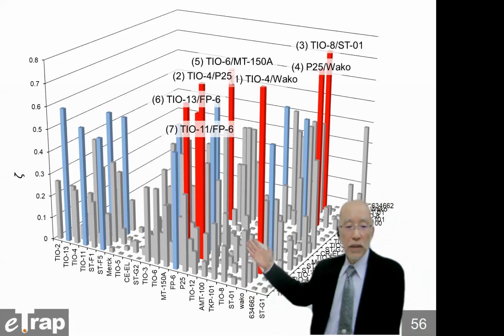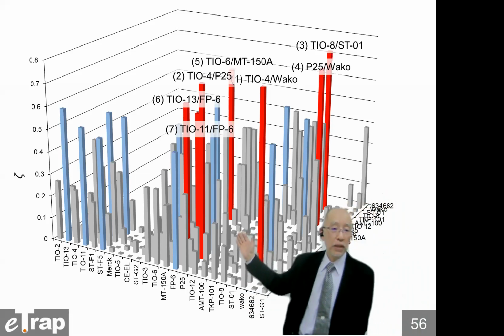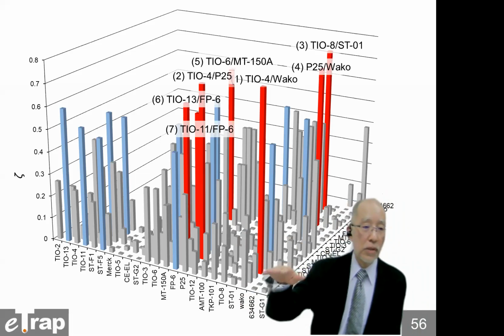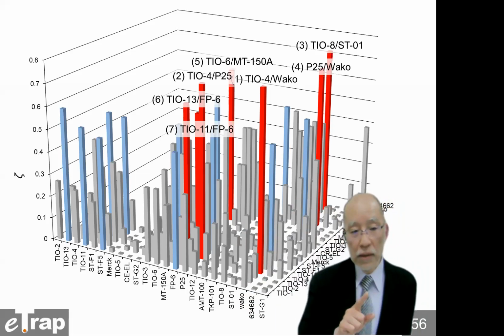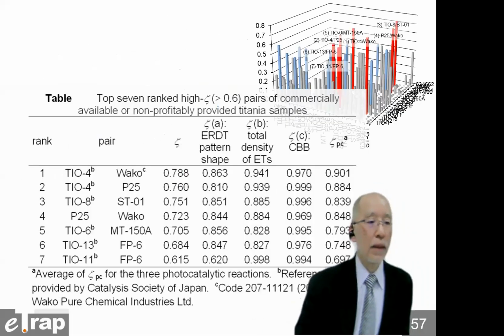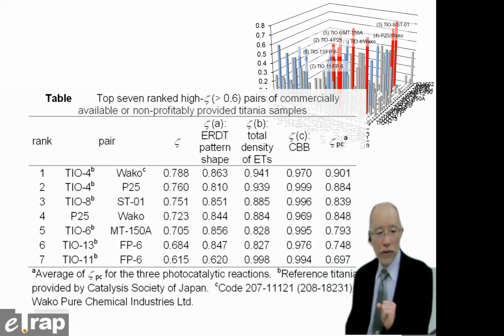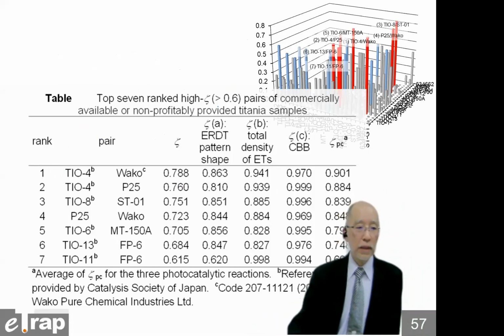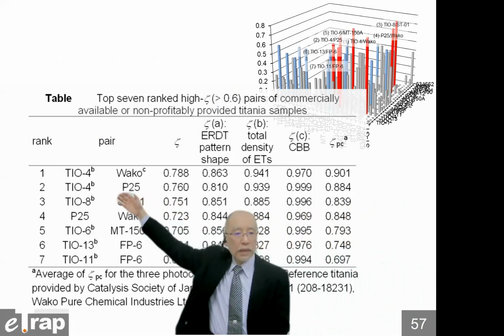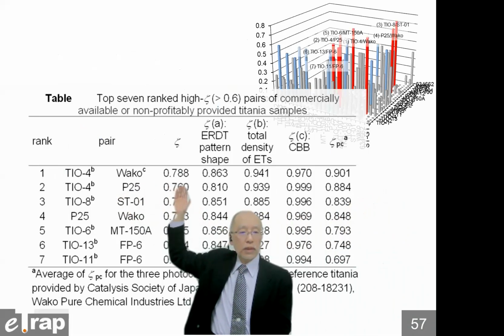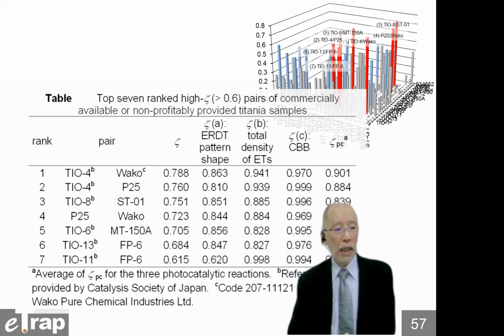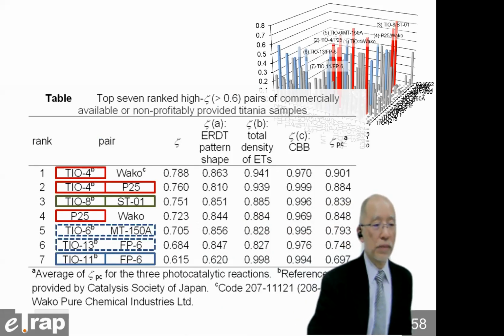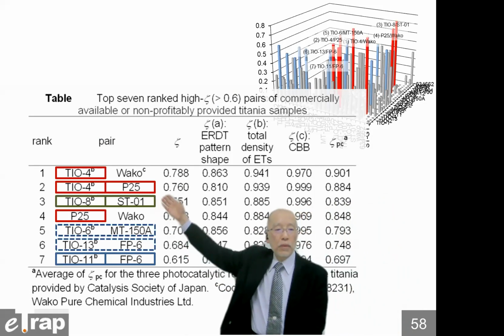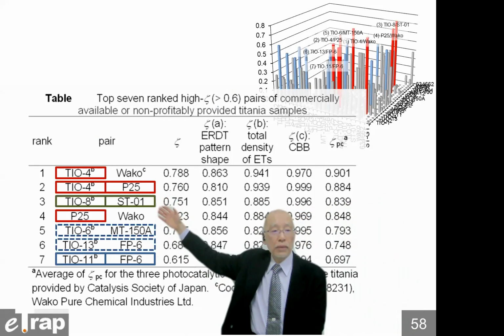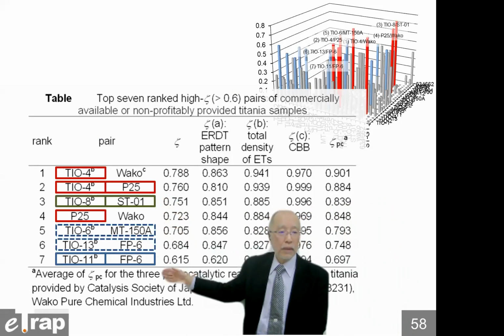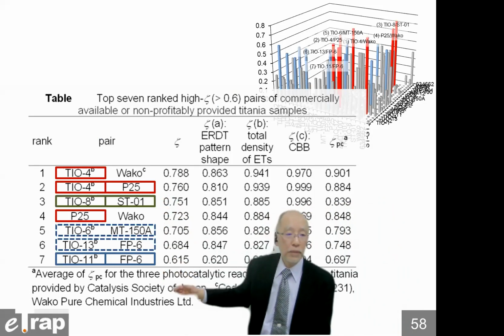But some pairs of titanium oxide samples give a total degree of coincidence higher than 0.6. So 6 red bars are here. And this is the top 7 pairs. The first one is TiO4, provided by the Catalysis Society of Japan, and the Wako sample, which gives a total degree of coincidence of 0.788. And an important point: rank 2 is TiO4 and P25, rank 3 TiO8 and ST01, and rank 7 TiO11 and FP6.